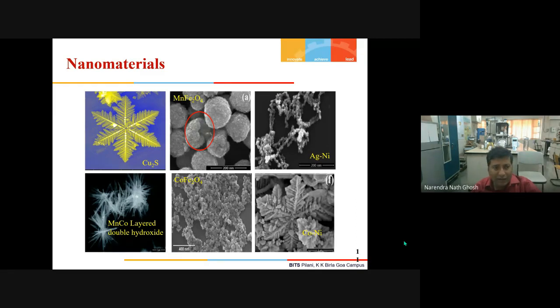We have synthesized these. You can see a beautiful dendrimeric structure of copper sulfide, and a hollow sphere; you can see the red ring and a broken sphere, which indicates that the spheres of manganese ferrite are hollow in nature. You can see small, tiny spheres of silver and nickel forming a chain-like structure. You can see needle-like structures of manganese cobalt layered double hydroxides, some spherical, and next spherical cobalt ferrite. In the corner there is a dendrimeric structure of cobalt where spherical nickel is attached. That means a cobalt nickel alloy has formed.